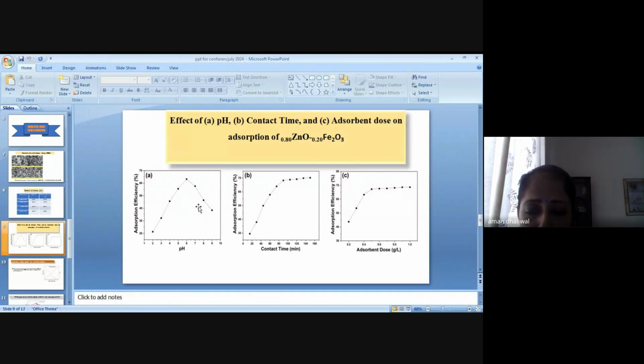This is because the charge on the surface of the adsorbent and the speciation of the uranium in the aqueous solution provide the explanation for the phenomenon. At the low pH value, between 2 to 3, the protonated adsorption sites electrostatically repel, while deprotonation and the emergence of the uranium species promote electrostatic interaction with the active surface sites of the adsorbent.